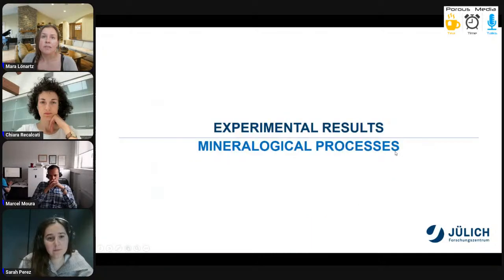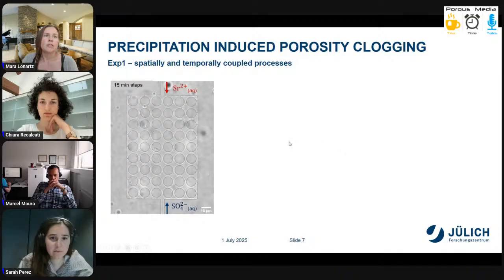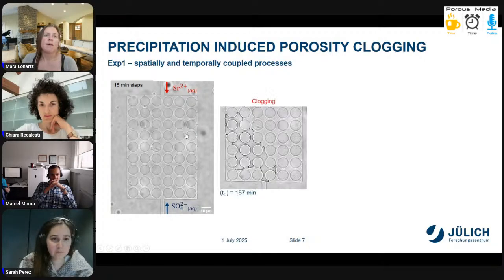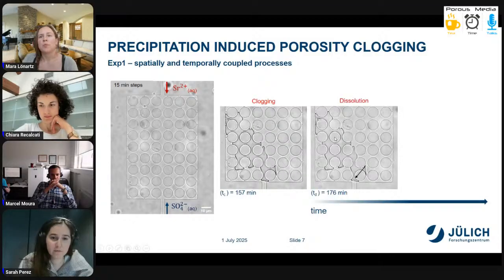Coming to the results, I will present two. The first one we can see here: we have the porous reaction chamber, and you can see how the celestine is growing, starting to nucleate in the center region of the chamber, and then finally clogging the inlet. And what we could see later, after just a couple of minutes, was that there was redissolution going on,